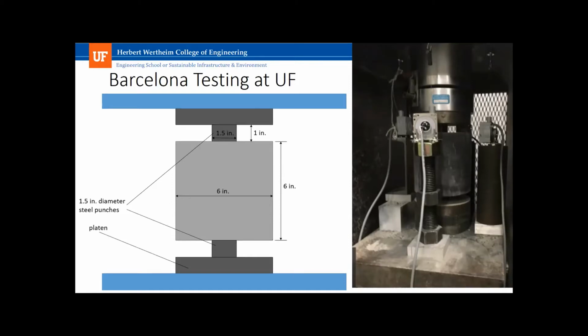This means that after the peak compressive load, as the load starts to decrease, you get an elastic release of the strains in the walls of the testing machine, which increases the rate of displacement of the sample. Now, this is a big problem if you have a material that cracks and is not ductile. You get a sudden release of energy and you get a sudden impact loading once a crack forms in non-ductile samples. And this leads to a lot of problems. The UHPC, however, if it's ductile, you don't get this sudden release of energy and impact loading when you start to get cracking. It gives you a very nice smooth response. At least that's what our hypothesis was.